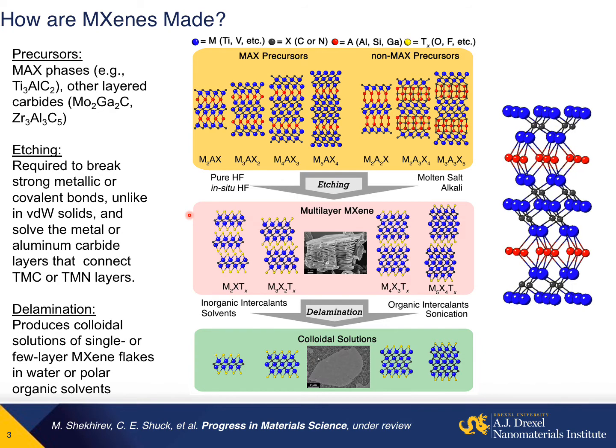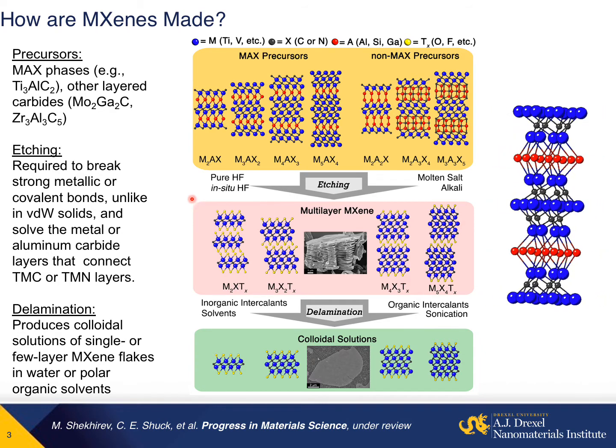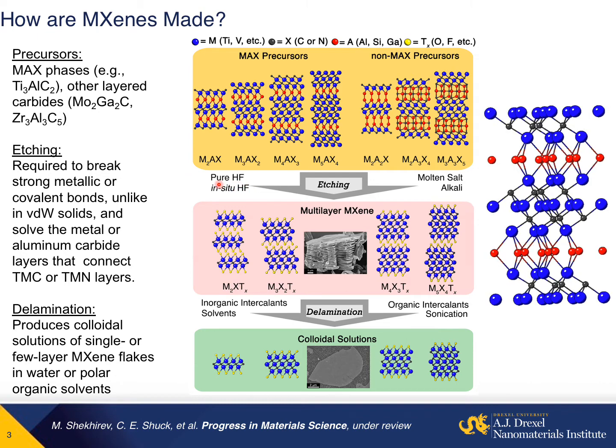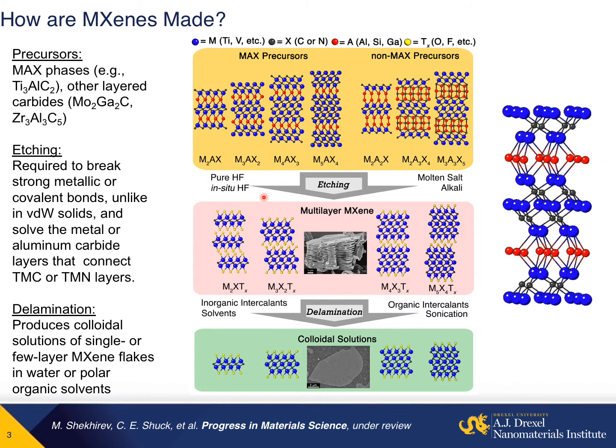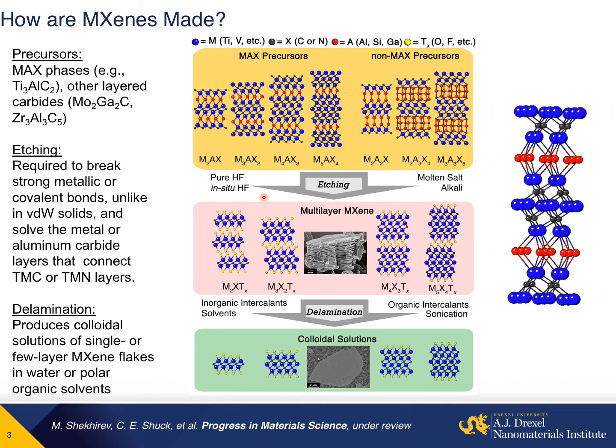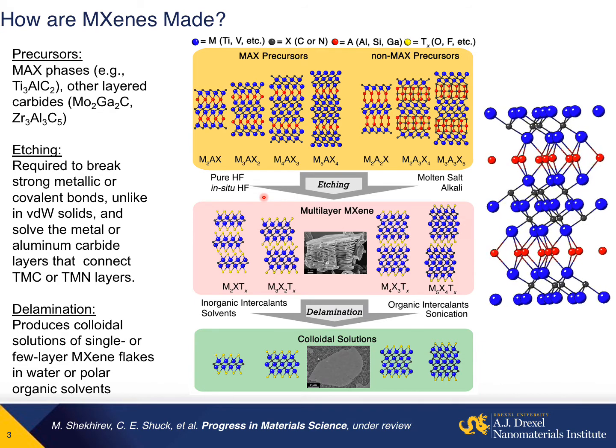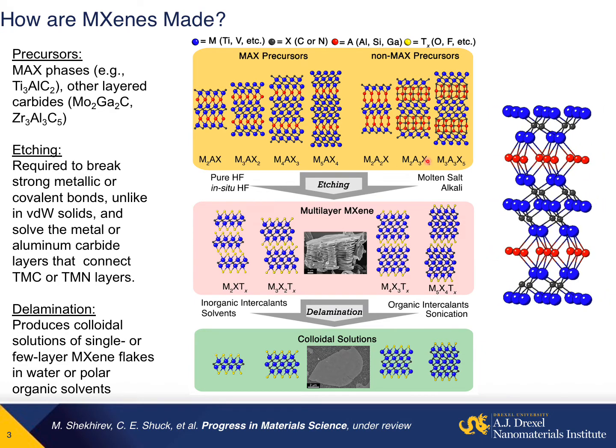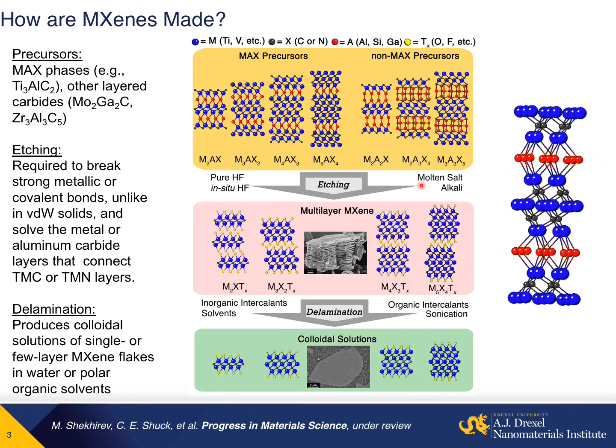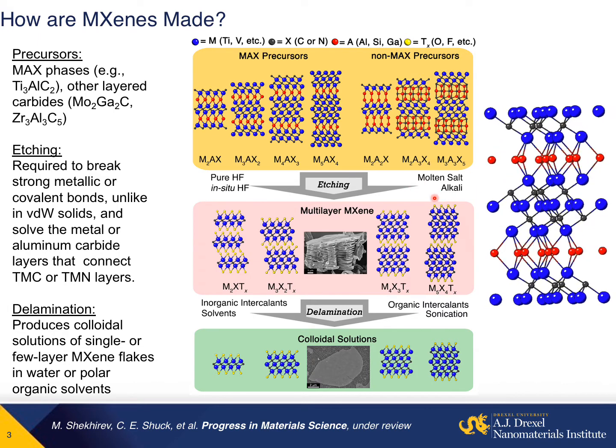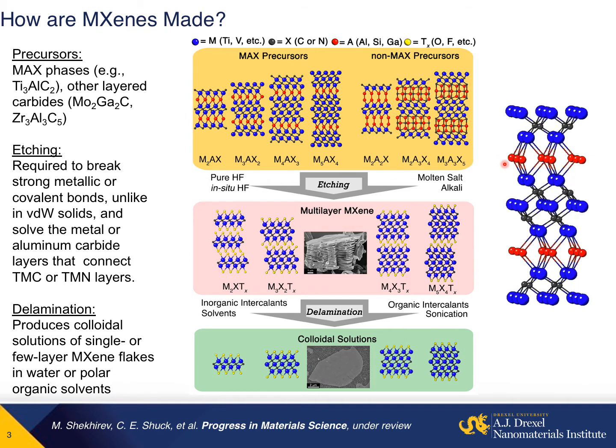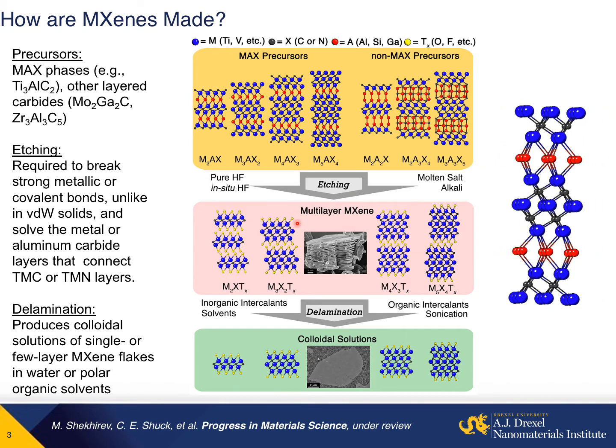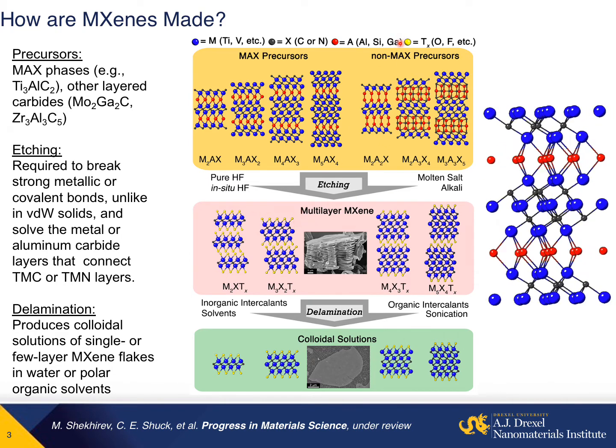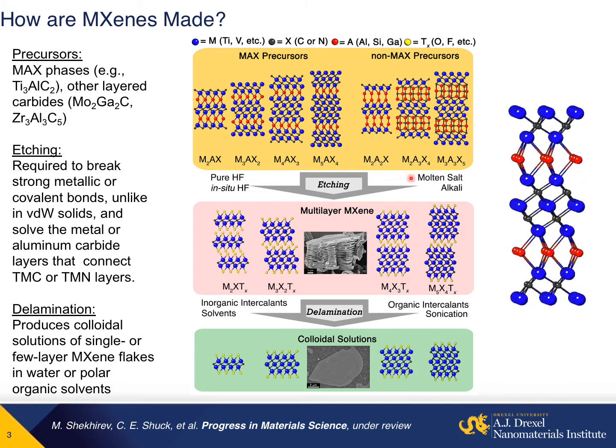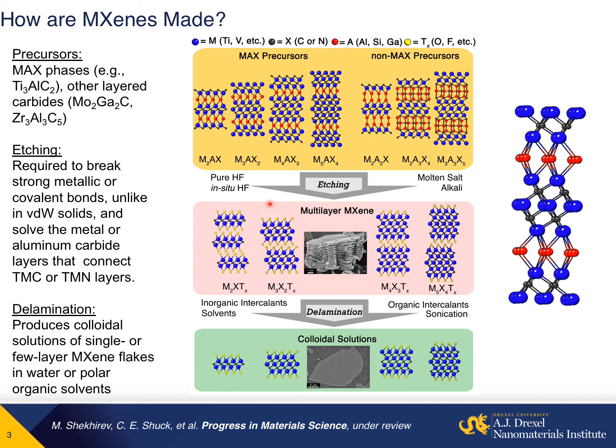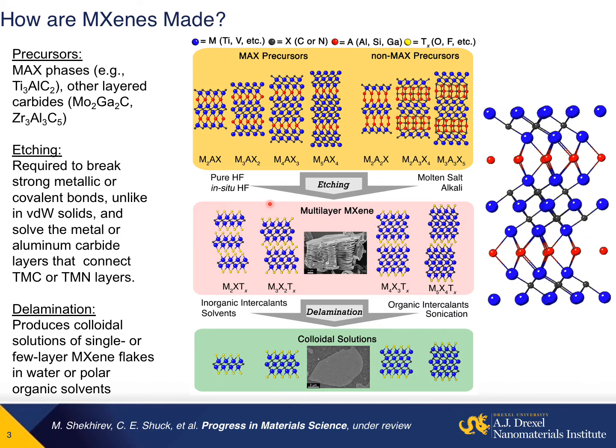When you submerge these ceramic MAX phases in an etchant, such as hydrofluoric acid or a mixture of an inorganic fluoride salt, such as lithium fluoride and hydrochloric acid, or recently using molten salts or an alkali extraction method, you will selectively remove the A layer, so this red layer here, and you will exchange that A element with a surface termination, so oxygen, fluorine, chlorine, or OH. And this is what gives it its natural hydrophilicity.